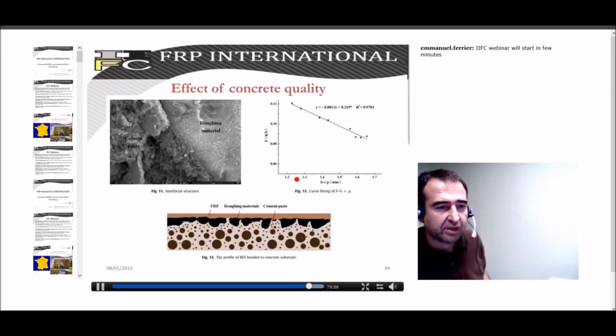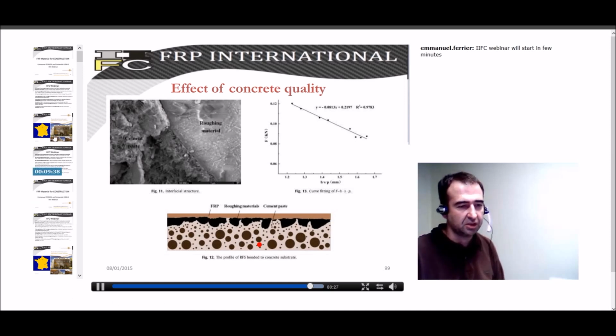The ultimate load depends on the aggregate size. This author has shown that the larger the aggregates, the lower the ultimate load at failure you will get. Essentially, as this small graph shows, depending on the porosity of the surface and the amount of cement paste, the strength of the complex is completely changed.